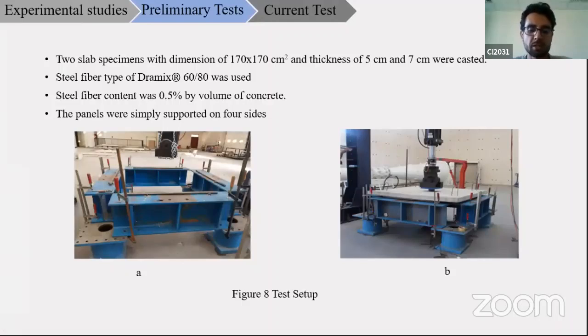In order to determine an appropriate slab specimen thickness for the final test, a trial study was carried out. In this study, 2 slab specimens were cast and tested with dimensions of 170 by 170 centimeter square, and thickness was 5 centimeter and 7 centimeter. A steel fiber type of Dramix with aspect ratio of 60 and length of 80 millimeter was used, and steel fiber content was 0.5% by volume of concrete.